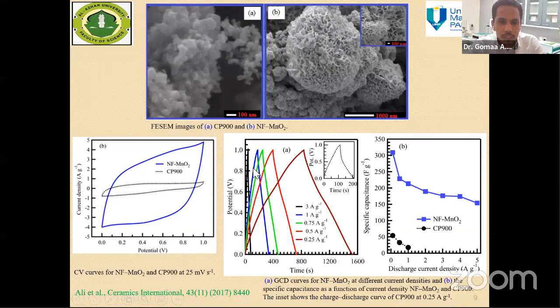The same manganese oxide recovered from this zinc carbon battery was tested for supercapacitor application, showing the rectangular shape in the CV curves. Here we compared with the cathode material before conversion, for example, the dotted curves for the cyclic voltammetry of the cathode powder. After conversion into nanoflower, manganese oxide shows a more rectangular shape and higher current density, indicating more charge accumulated or stored in the manganese oxide nanoflower shape.